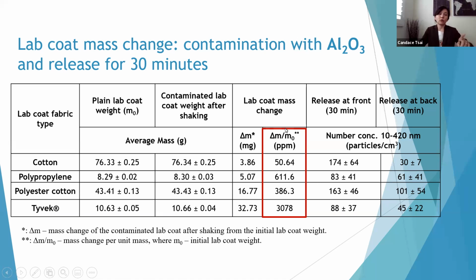This is mass data we measured before and after, so we look at the differences in lab coat mass change. If we divide the difference by the original lab coat weight, that gives us delta M divided by the original lab coat weight, showing the percentile change, but it's too small, so we show it as ppm.